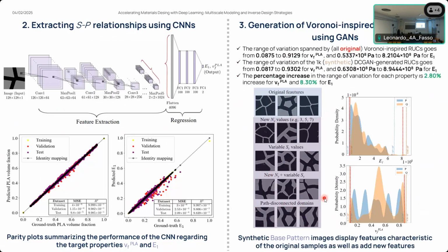Numerically, we can characterize that by creating a data set of 1,000 synthetic samples and computing the effective properties associated with this synthetic sample. We observe an increase in the range of variation of the effective properties compared to the range of variation associated with the original data, which is very important and exactly what we need to exploit in order to achieve target points that are not inside of the original training data distribution.